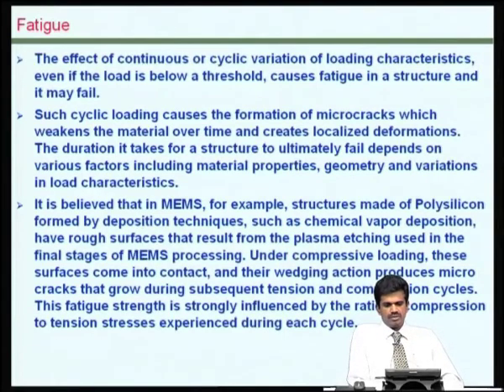Fatigue is another long term contributor for the failure of microsystems. Due to cyclic loading, micro cracks may form on these microstructures, which essentially aggravate over a period of time and cause ultimately failure of this part. Many structures in microsystems are made of polysilicon, and which are made by deposition of thin films. These have rough surfaces caused by etching and other process steps, and when these are subjected to compressive loading, there could be wedging action which could produce these micro cracks, and that can affect the characteristics of these structures.